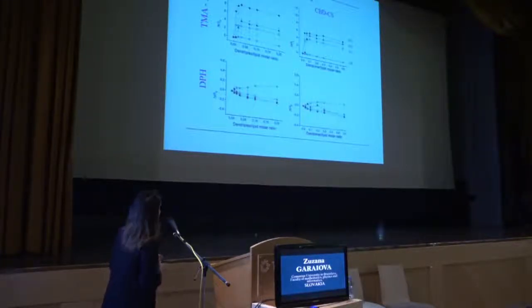Let's check those dendriplexes, how they can interact with the hydrophilic part of lipid vesicles. And what was interesting is that when we increased the molar content of PEG, the interaction was weaker.